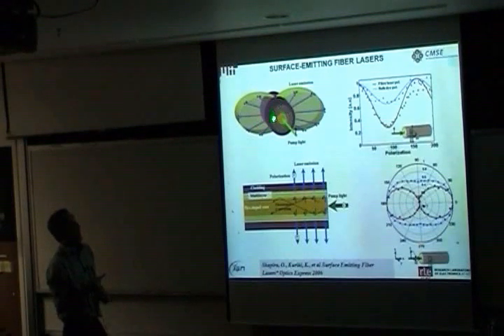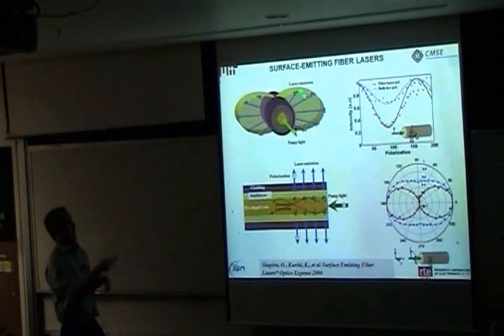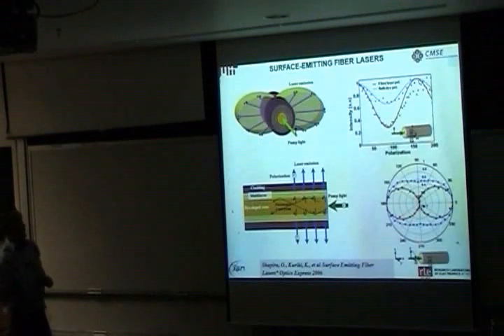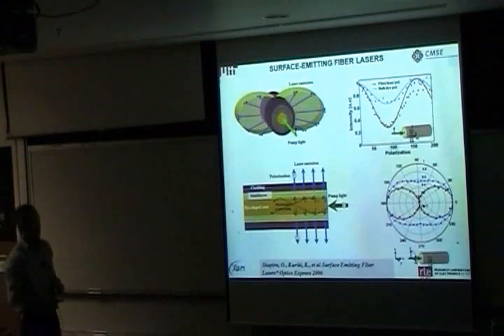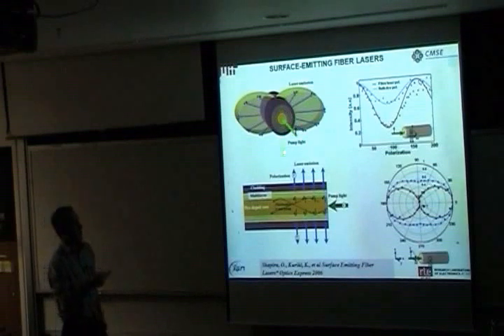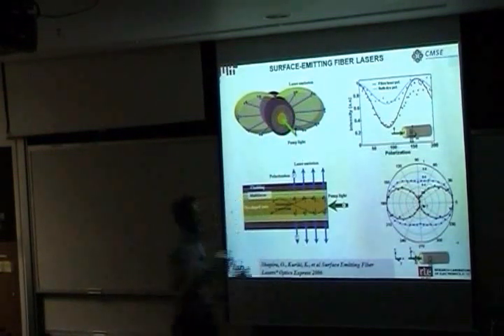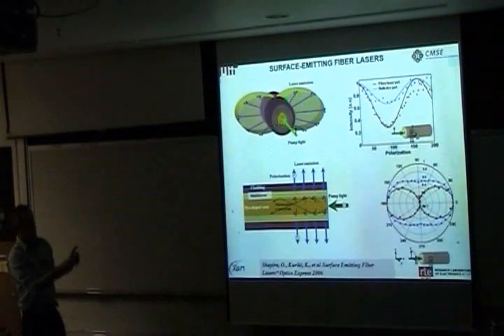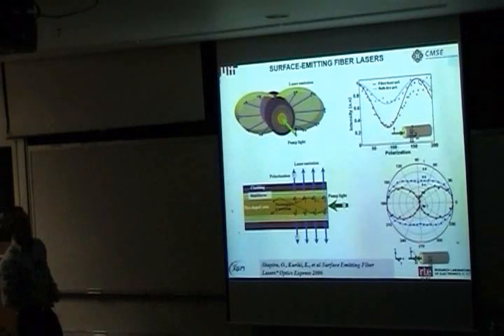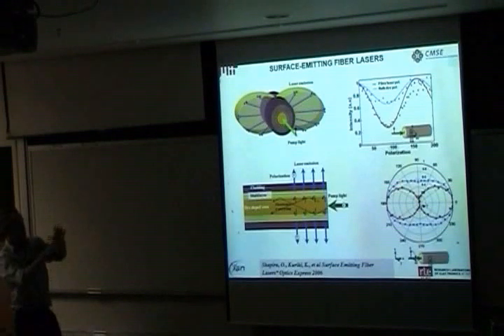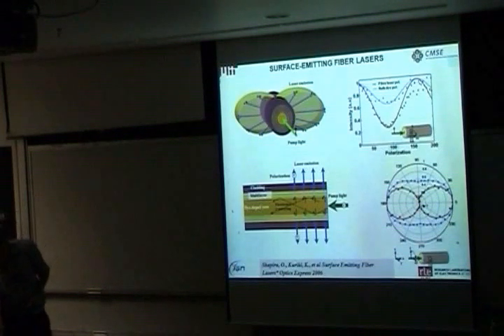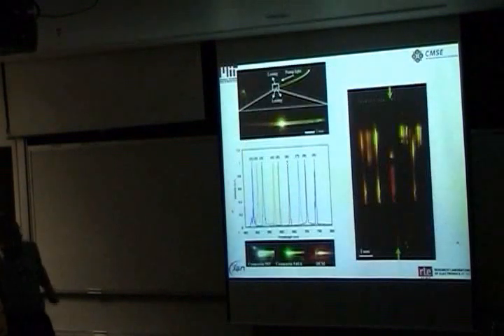Now, initially, we thought that since the structure itself is cylindrically symmetric and the gain medium inside is isotropic, we should get a wavefront that shares those same symmetries, namely a cylindrically symmetric wavefront. What we in fact found was this dipole-like wavefront. And that really is a result of a breaking of the symmetry, and the breaking of the symmetry is associated with the linear polarization of the pump light. So if you go from linearly polarized light, in which you get these two lobes emitted in the direction perpendicular to the direction of your electric field, to a circular polarization, you actually recover your cylindrical wavefront. Basically you could use these to create very simple fibers for emitting light or for displays, and by putting in different gain media, you could actually get these to emit in blue, green, and red.